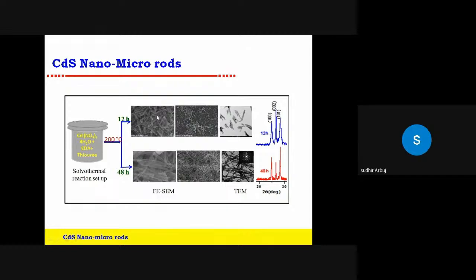In both cases, we got the rod. Here the length of the rod is lower, up to 200 nanometers. But here, the length of the rod drastically increases. Its length is up to 5 micrometers. And from XRD also, we see the 002 peak intensity is higher, which means the rod length is higher here, lower there.